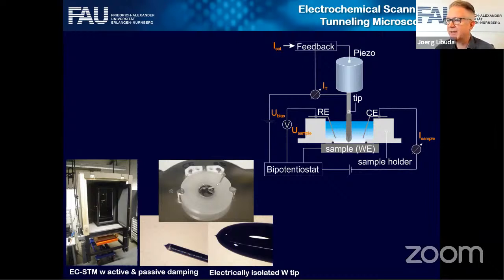So to start with the microscopies, one important microscopy is scanning tunneling microscopy, and you can apply this microscopy under electrochemical conditions. So that's the schematic setup. The sample would serve as a working electrode, and then you have your three electrodes set up. And there's a fourth electrode, that's the tip. And you immerse the tip into the electrolyte.